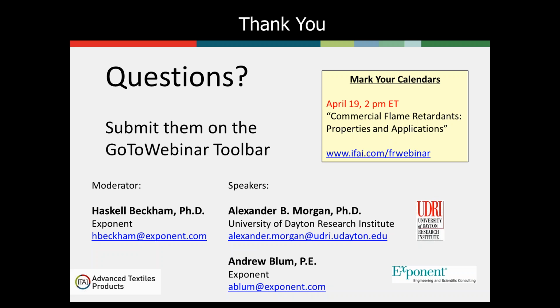Yeah, good question. This comes up a lot, because you'll hear from people that, hey, we tested one day at this lab and everything was fine, and then we tested the exact same thing at a different lab 2 months later, 6 months later, 1 year later, and we got a completely different result. So one of the things you need to do, anytime you're running any test, is to remove as much variability as you can: following the procedure, making sure your equipment is calibrated and operating properly, that you're getting the right result.